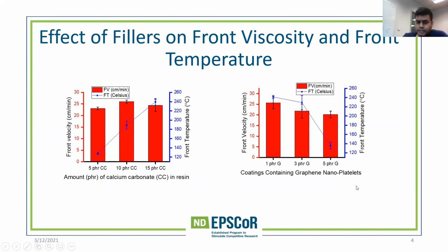With graphene nanoplatelets, we were only able to load 5 PHR because these are nano in size and occupy a lot of space. The front velocity decreased with the increment of graphene nanoplatelets because in the research it is previously shown that graphene nanoplatelets quench the front. They uptake the free radicals and slow down the front. Also, we see a decrease in the front temperature, which is complementary to the previous findings.